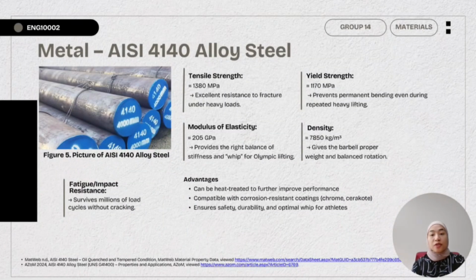AISI 4140 alloy steel is the most ideal material for the Olympic barbell because it has the most balanced mechanical performance. First, it has very high strength. Tensile strength is around 1380 megapascal. Yield strength is around 1170 megapascal. This value means the bar can withstand extremely heavy load without breaking and won't permanently bend even after repeated use. Next, its modulus of elasticity is around 205 gigapascal, giving it the ideal stiffness. This is what provides the whip during Olympic lifts, helping athletes build momentum.